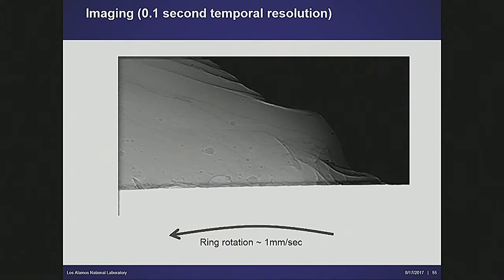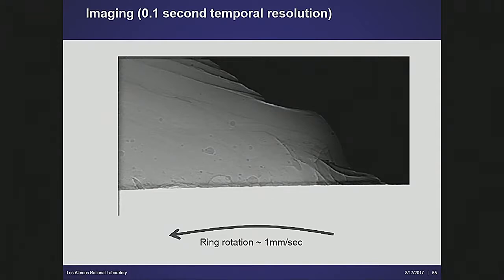If you notice closely, just at the end there, when you start it, it contracts. So it's still moving, you can see it shrinking, and then you end up with these light features. Right now, I'm not ready to say whether these features are at the surface, but some of them are porosity in the leading edge of the weld. It's easy enough to see them after it's frozen.